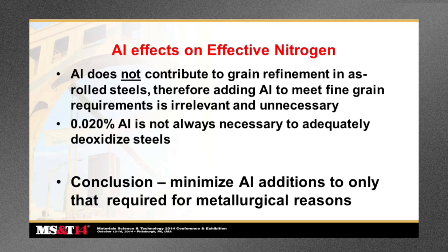So we know that aluminum does not contribute to grain refinement in the as-rolled steels, which is primarily where you use any microalloying system, as-rolled or as-forged. Therefore, adding aluminum to meet any fine grain requirement is in fact irrelevant and unnecessary. Yet it seems to be very common throughout the industry to request aluminum fine grain material, which in the as-rolled condition is in fact meaningless.